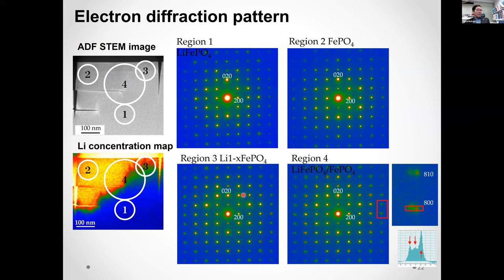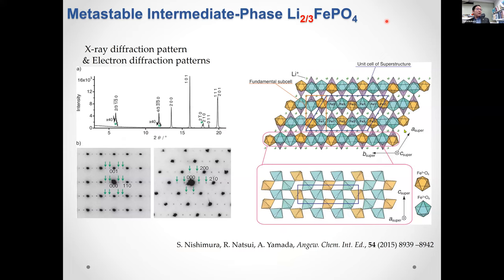And we tried to analyze this diffraction pattern and found it corresponds to two-thirds LiFePO4, like that. And Professor Yamada of the University of Tokyo artificially synthesized lithium two-thirds FePO4, and he obtained the diffraction pattern like that. This small satellite spot is consistent with our spots, this spot. Then we can determine that the intermediate phase was lithium two-thirds FePO4.